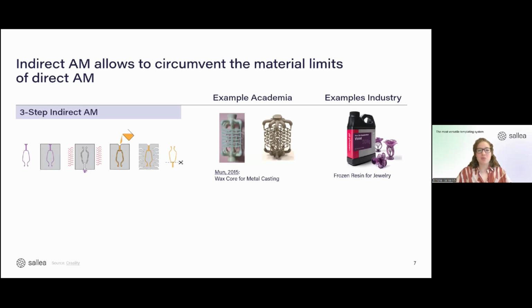And I think it is still being used and also known in the composite industry, for example, for making wax cores that can be molten out, where usually you first 3D print a plastic material, here shown in purple. Then usually you cast the silicone mold around it. You take out that first material that you printed before you can actually print, for example, the metal that you want to have, remove the silicon core to actually get your mold. So it's a very lengthy and tedious process.